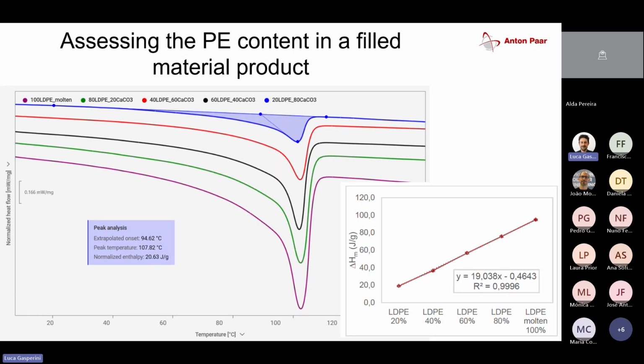I just said that we can fill a material with various components for improved characteristics. So that's the case of a polyethylene and calcium carbonate. Mixing polyolefins with calcium carbonate can happen for several purposes. First, the filler is much cheaper than the polyolefin. It increases the stiffness and improves the processing or optical or surface effects. So the properties of the final product can actually be fine-tuned by the right content of the filler. And DSC is also a good tool to monitor this content.